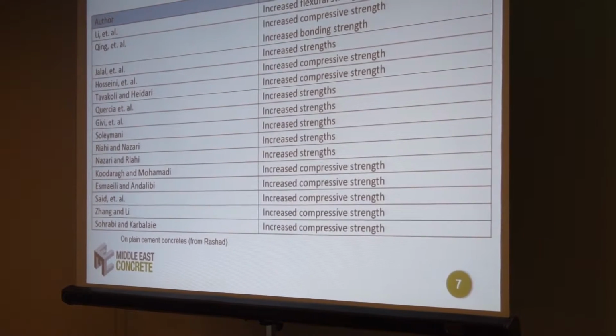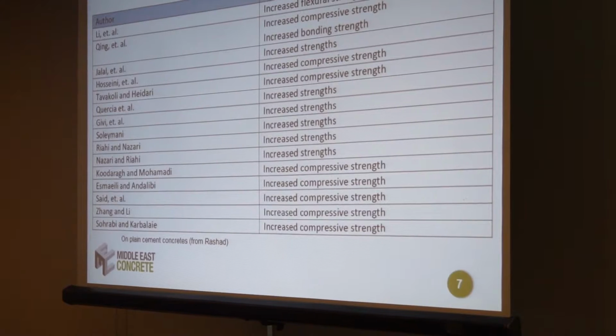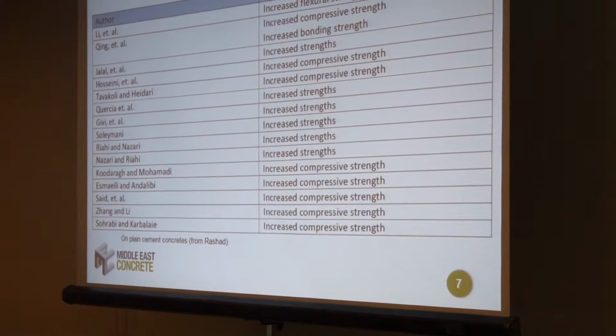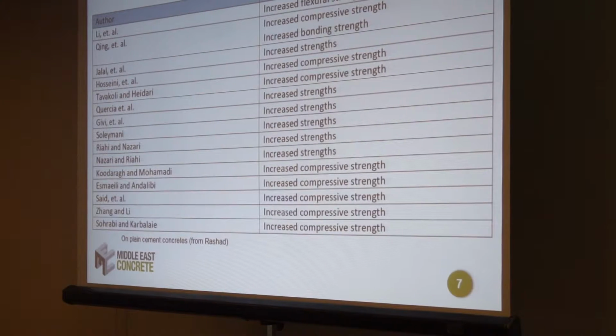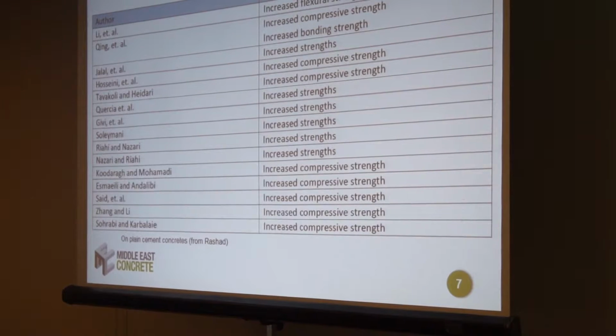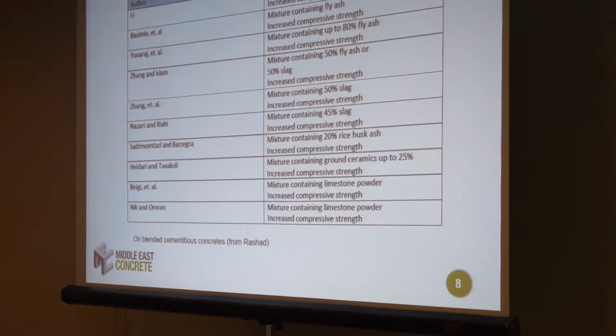So I want to share some compressive strength effects. These are from researchers, not me. These are previous researchers in the field. And not all of these are post-applied. Some of them are colloidal silica used as an integral admixture in the concrete. But the effects are the same. And you can see this great lot of researchers have all demonstrated increased compressive strength. There's some thrown in there: increased flexural strength, increased bonding strength, etc. This is just continuing, the researchers that have shown those strength improvements by using colloidal nanosilica.